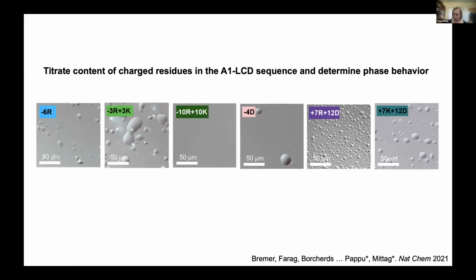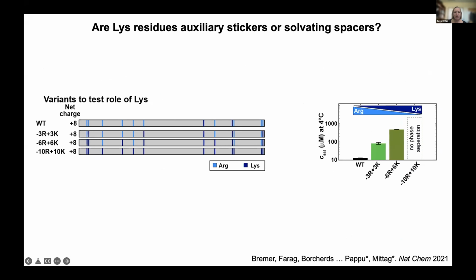You see that they make, in principle, nice condensates, except for this one sequence here, where we're replacing all arginines with lysines. And indeed, when Anna in my lab replaced more and more arginines with lysines, this weakened phase separation until there was no phase separation visible anymore, really showing that lysine residues are highly solvated spacers.